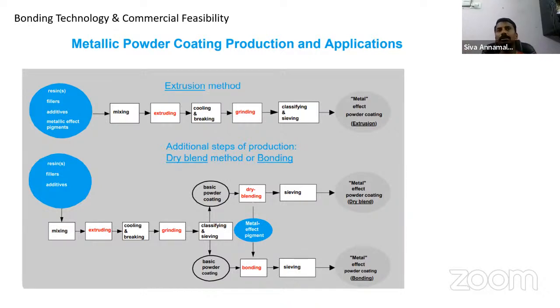What is the advantage? You need not add anything after completing your production. It means your time is saved. Any color you want to fix, you can fix at the stage of premix. This is one point. But what is the negative aspect of this process? Actually, you will get a dull effect. I mean, your metallic effect or luster effect goes away when your metallic pigment is subject to high shear in the extruders. So this is a disadvantage.